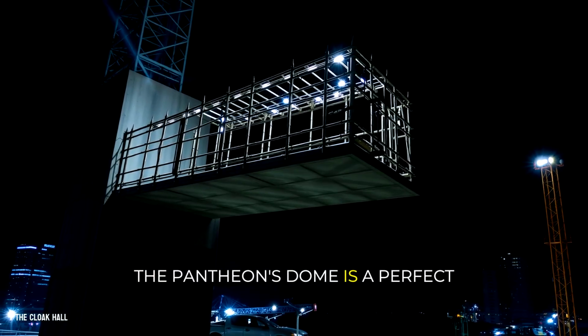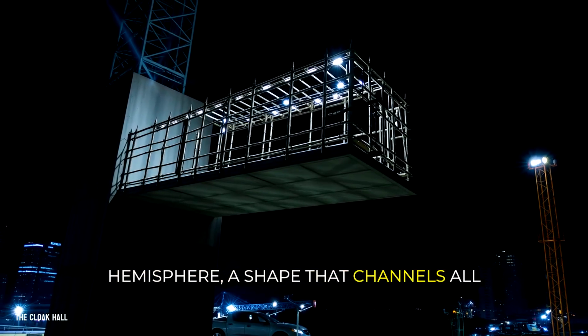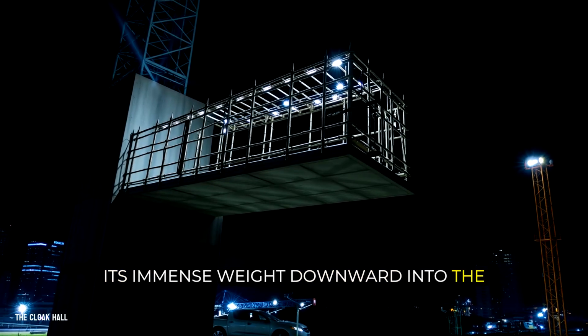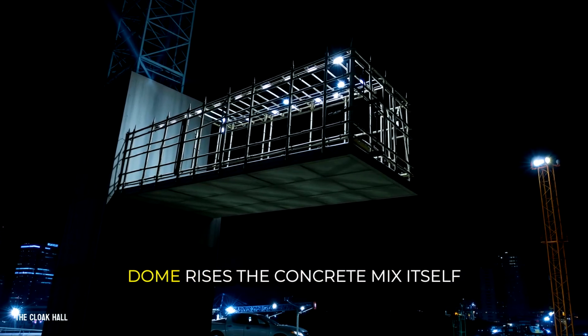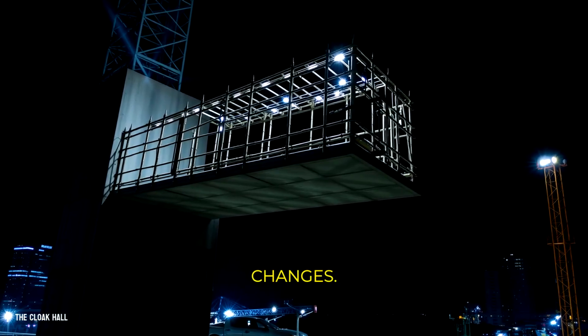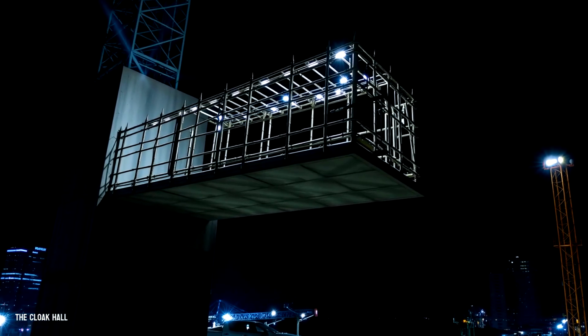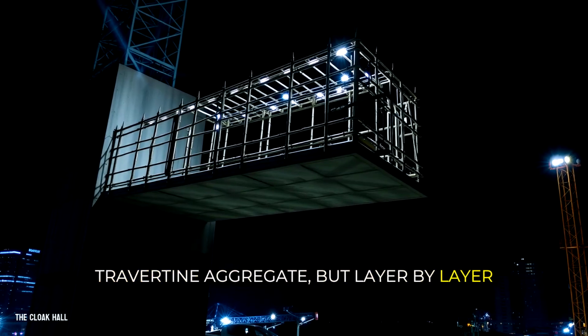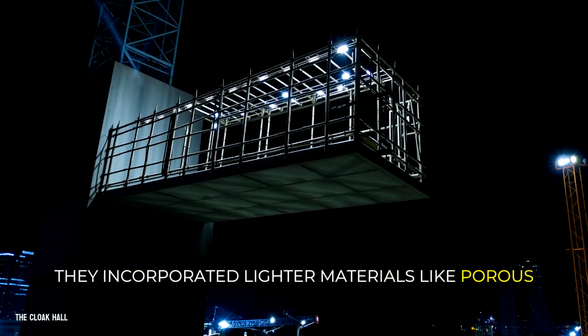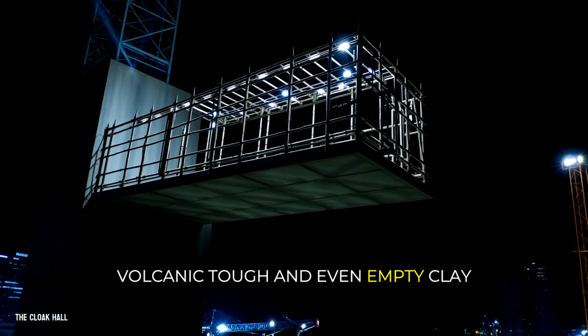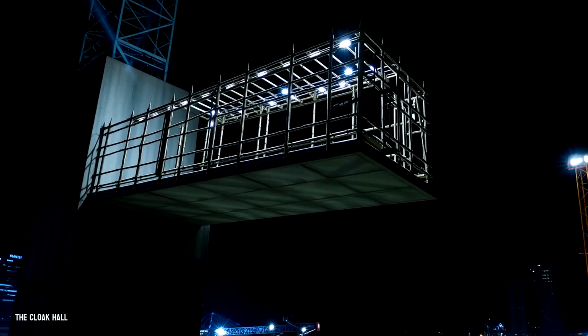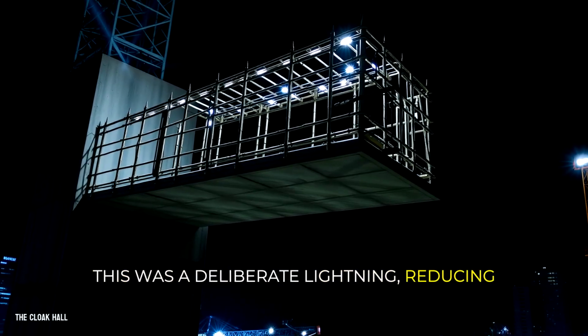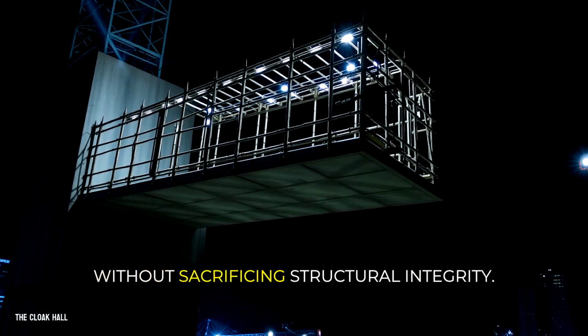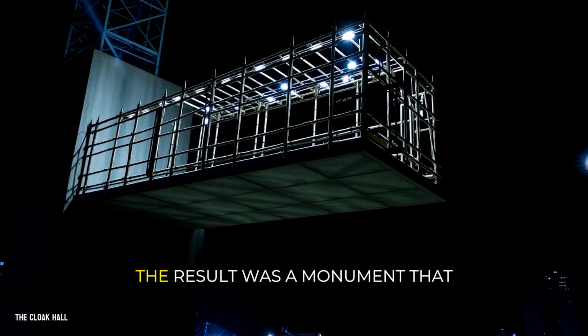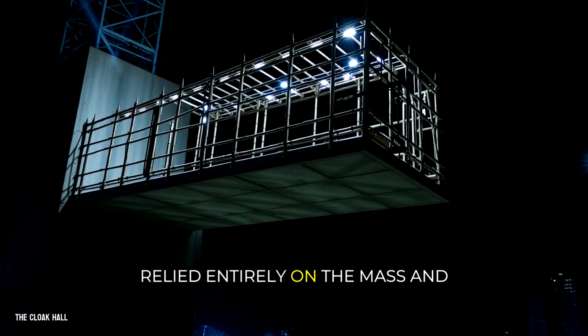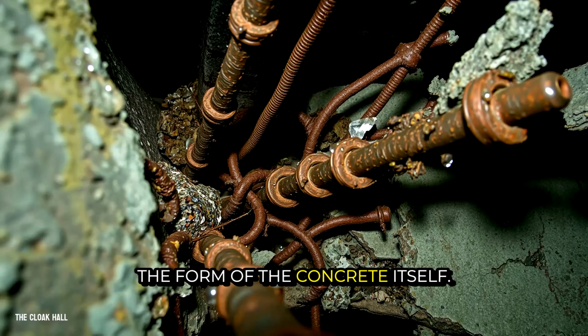The Pantheon's dome is a perfect hemisphere, a shape that channels all its immense weight downward into the supporting drum wall, and as the dome rises, the concrete mix itself changes. At the base, they used heavy travertine aggregate, but layer by layer they incorporated lighter materials like porous volcanic tuff and even empty clay amphorae at the very top. This was a deliberate lightening, reducing the load on the lower sections without sacrificing structural integrity. The result was a monument that relied entirely on the mass and the form of the concrete itself.